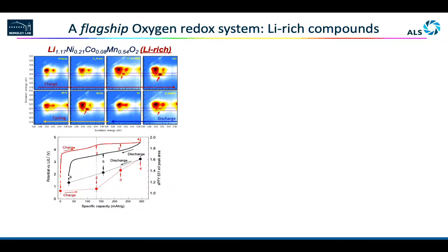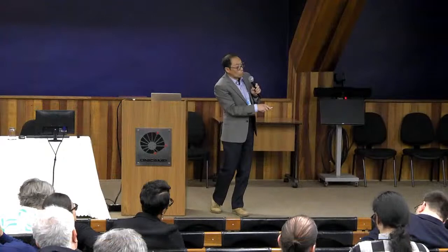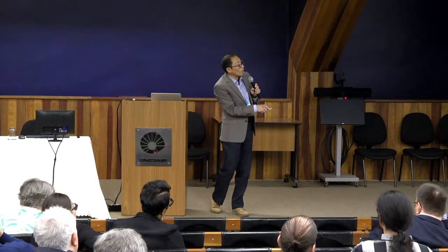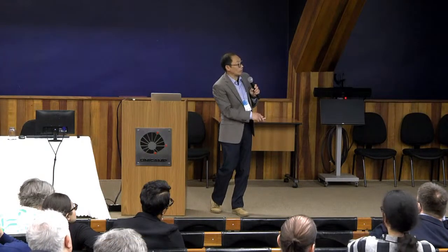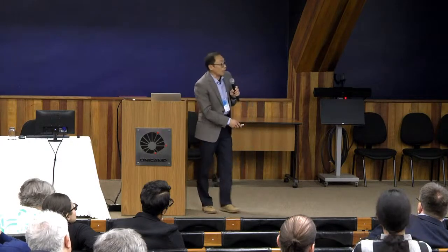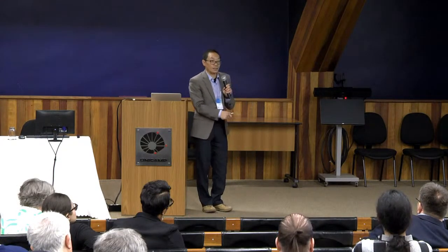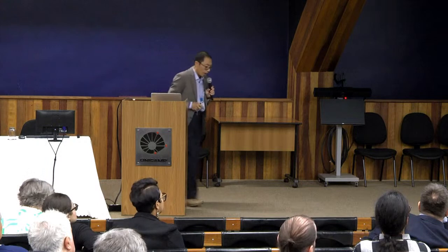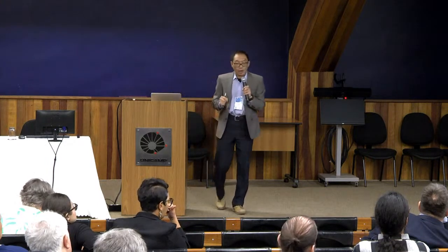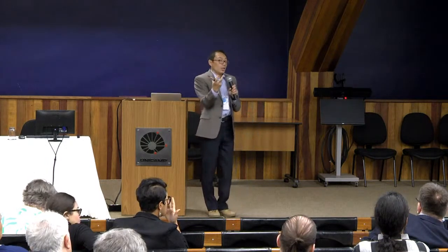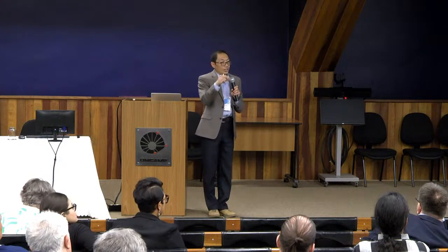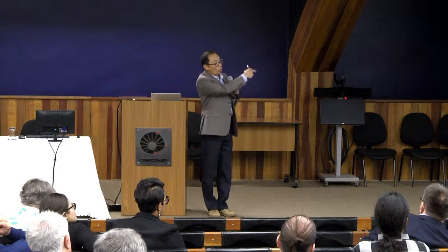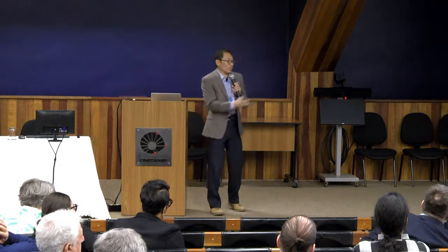And I also told you it does show inside the material this feature showing up and discharge going away. And I also mentioned this material has the oxygen gas release in there. So it's a combination of oxidization of oxygen. However, if we look at the RIXS finding of the oxygen oxidization and reduction in the material, because all the RIXS experiments were done in ultra high vacuum, of course, if it's released, it will not be here.